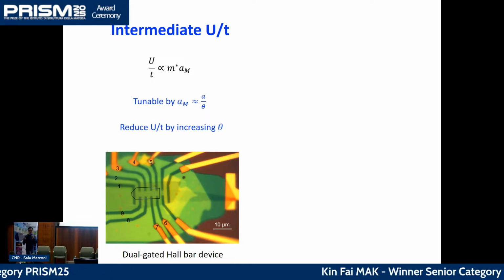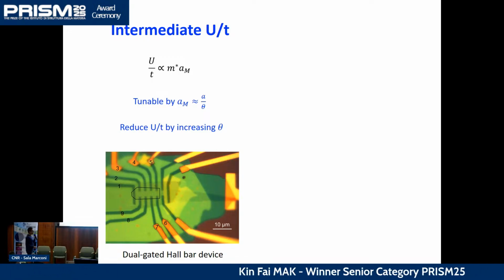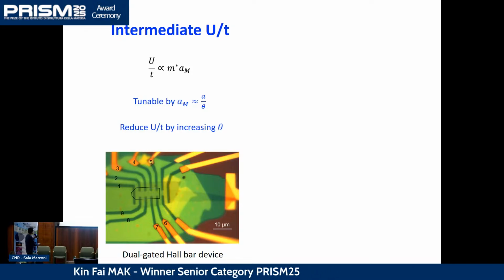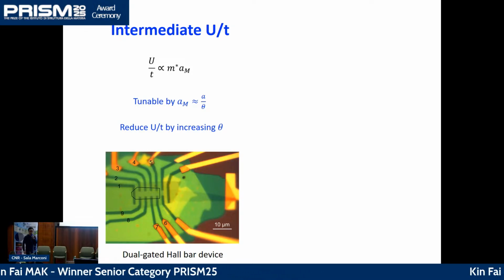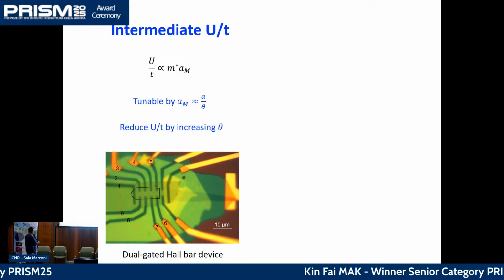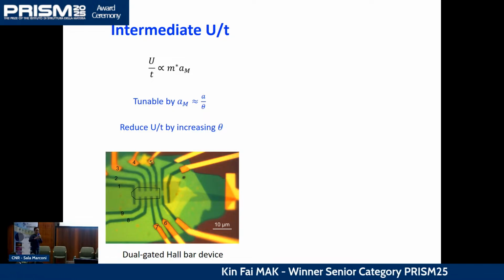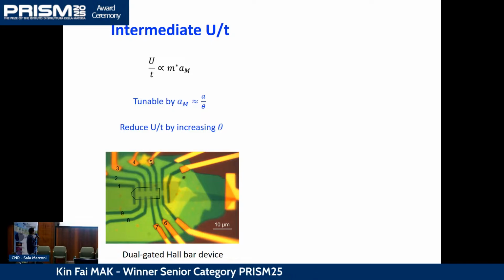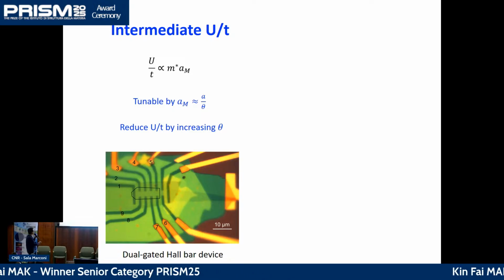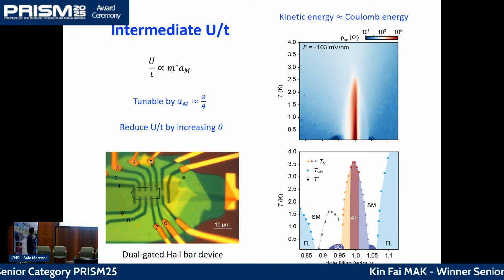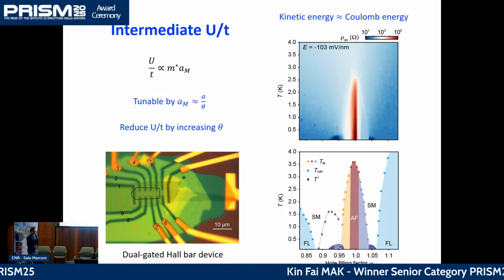Now I'm switching from optical probe to electrical probe. This is actually the twisted sample, which is directly connected to these electrodes here, so that we can measure the resistivity of the sample quantitatively. Also with the gates, so that we can actually tune the density continuously. So let me just give you one example. By just reducing this U over T ratio here, this is the kind of phase diagram that we can get.